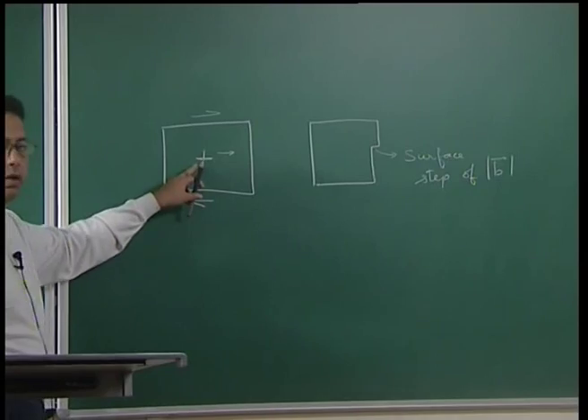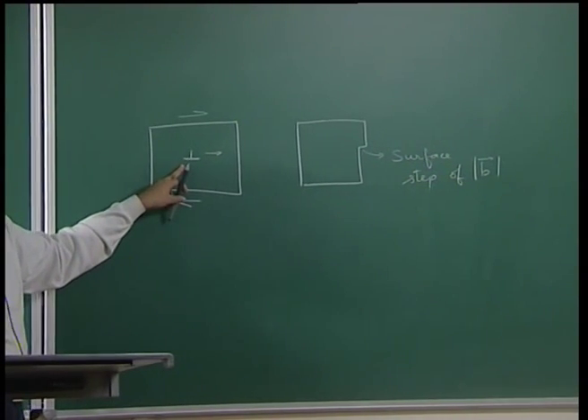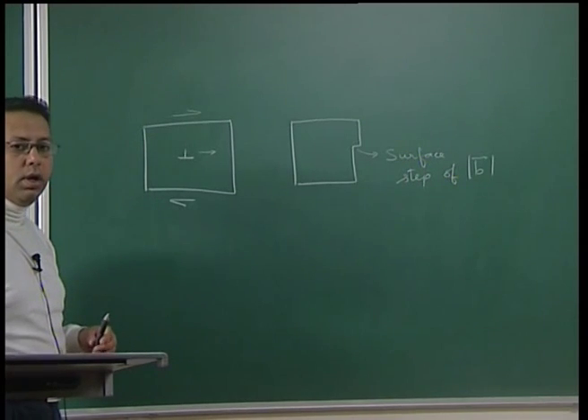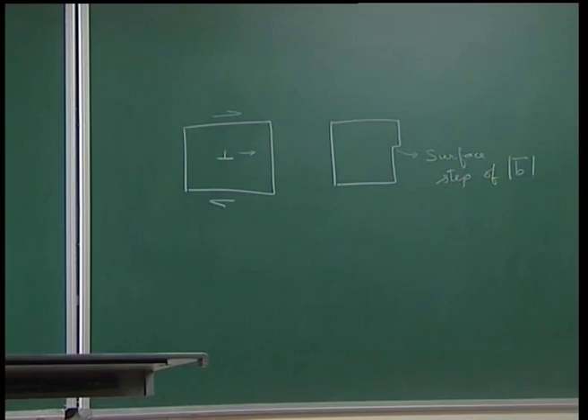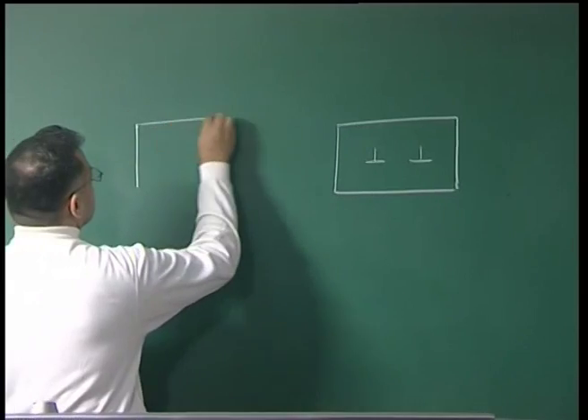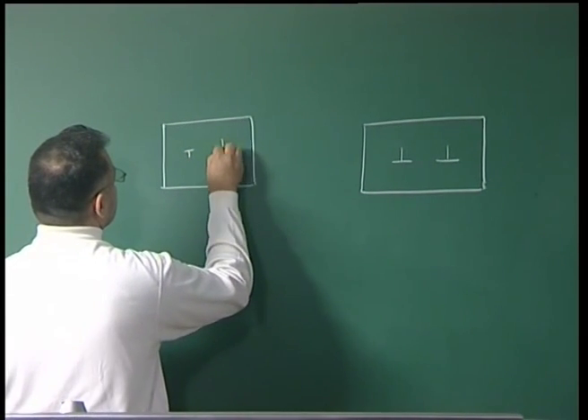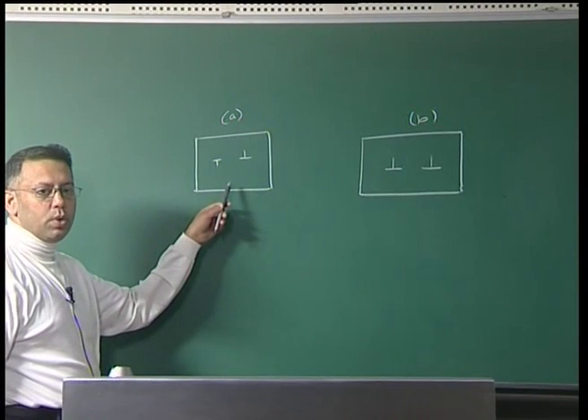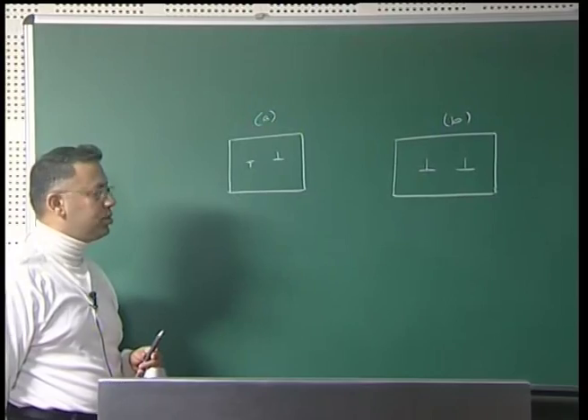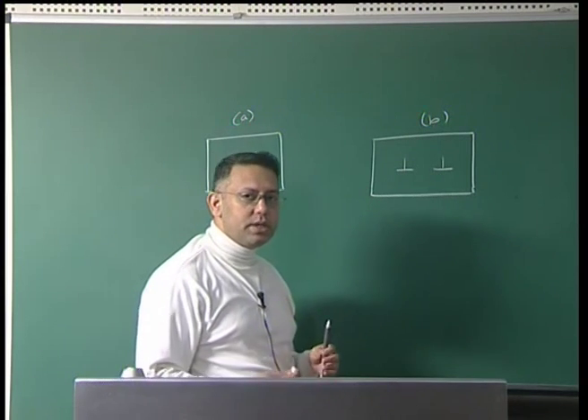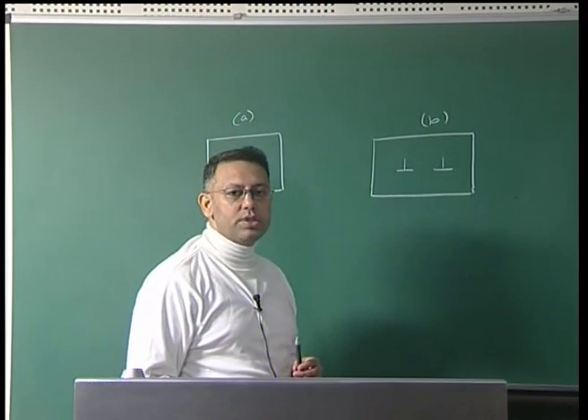In other words, I have an internal defect — an edge dislocation — and the external stresses interact with the stress field of the dislocation, driving it to the surface. If I consider two dislocations in the material, there are two configurations: in configuration a, the two dislocations attract each other; in configuration b, they repel each other. The agency by which this interaction is mediated is obviously the long-range stress fields of the dislocation.